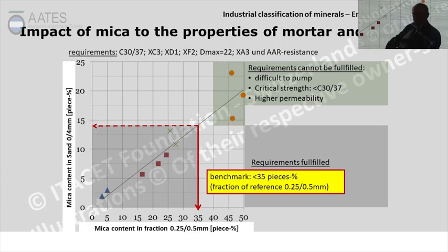If we do that, the construction company asks us, okay, can I use this for concrete production, yes or no? You can use this product in this range of mica for concrete, but you couldn't use it if the mica is up there, because it gets much more difficult to pump the concrete, and the strength you cannot reach. And that's why it was fixed that the mica content must be lower than 35 piece-%, measured in the range 0.25 to 0.5 millimeters.